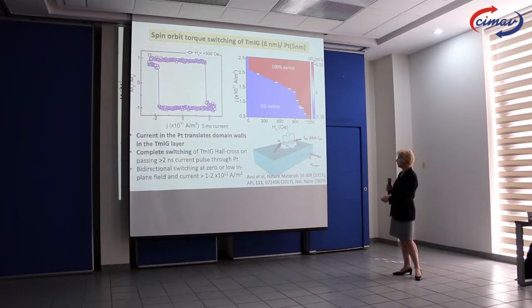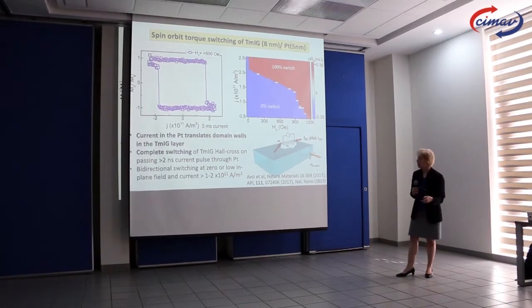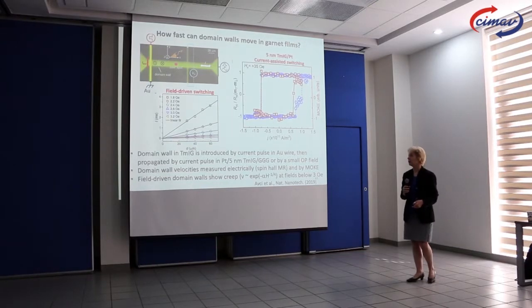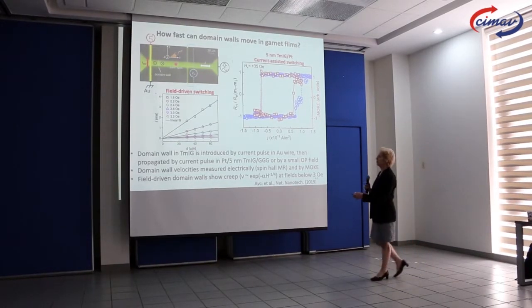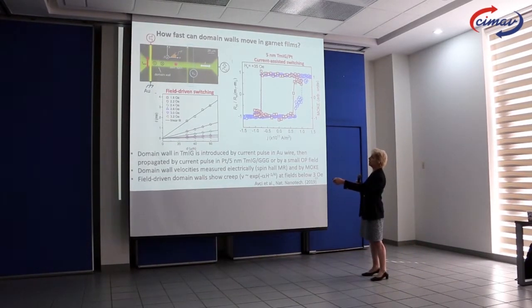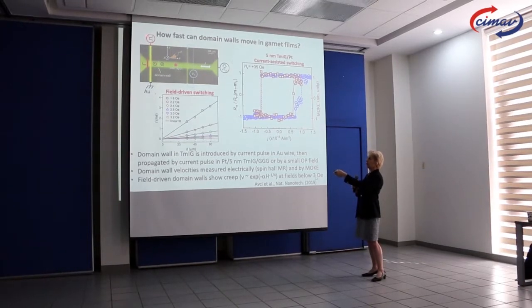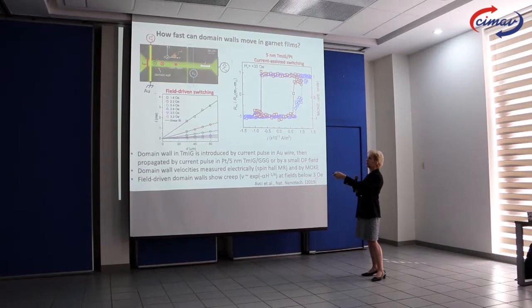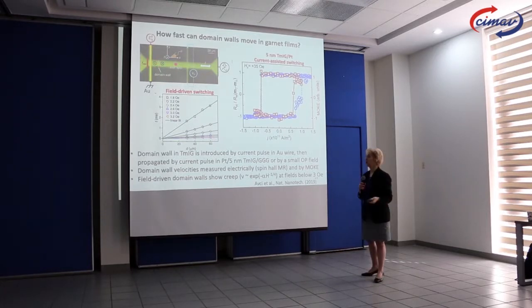So this is the first time we did this. This was 2017. And then since then it's been improved quite a lot. So this is what the structure looks like now. We have a Hall cross still, there and there, in the garnet with the platinum on top. But we also have a gold wire on top, which can be used to produce a domain wall. By flowing a current through here, you make an Ørsted field and it makes a domain wall. And now the current in the platinum can push that domain wall around in a very controllable way.